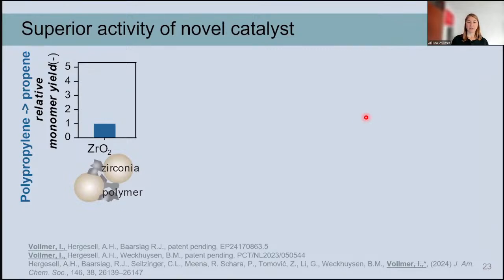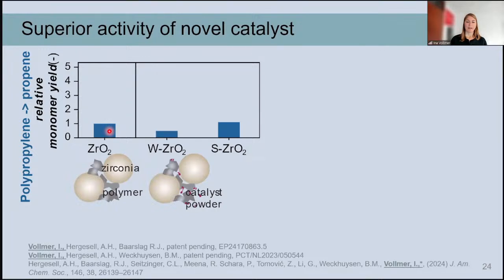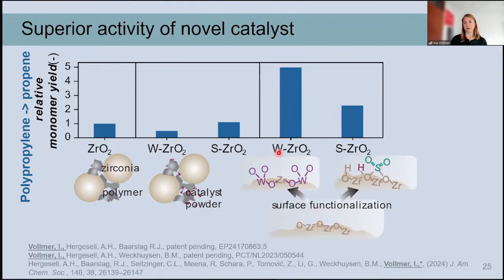And so to demonstrate that this really has a benefit, you see here a polymer converted with commercial zirconia grinding spheres. So there's already some propene formed, which I normalized here to 1. And then we added both tungstated zirconia and sulfated zirconia powder to the ball mill, and you see that there's no increase in activity. However, when we actually functionalize the surface of the grinding spheres directly, we do see a marked increase in activity.